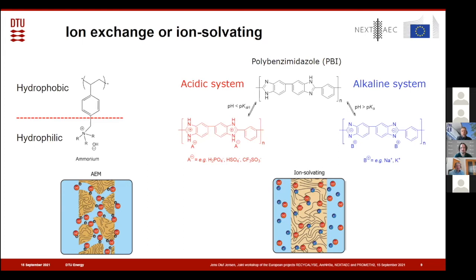We just have polymer materials, exemplified by the polymer polybenzimidazole that we have used a lot and Blue World is using for fuel cells. Then it's doped with acid, and you get this acid and polymer mix that is highly conductive. That's phosphoric acid. You can go to very high temperatures because it doesn't evaporate as easily as water. And we can also dope it in the alkaline system with aqueous KOH, and then we get an alkaline ion conductor. And that works famously, but the stability of the PBI in the alkaline system is not good enough as we know it. So that's one of the things that we're looking at in the project. How can we improve that? Also, we make other completely different polymers with high alkaline stability and also the hydrophilicity it takes to suck up the electrolyte and form the ion solvating membrane.